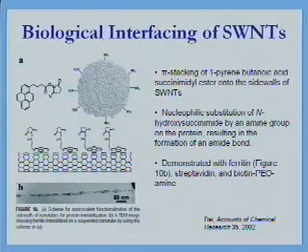And the other area of application is where you do biological interfacing with nanotubes. So this is a very simple example. What you do is, you have a single wall nanotube. You absorb this 1-pyrene butanoic acid ester due to the pi stacking, and then you do nucleophilic substitution with the NH2 of the protein molecule, to get this absorption onto the nanotube. So in this picture, it's shown how the different ferritin molecules are absorbed on a single wall nanotube. And this application may find use in different kinds of sensors or biological detection elements and something like that.